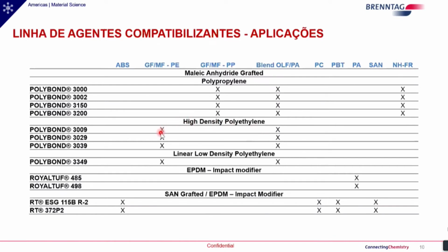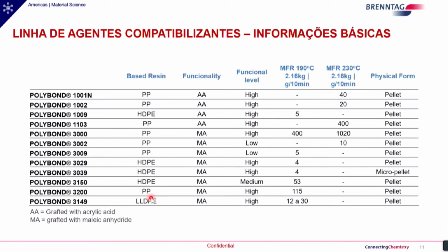In our line of products, we also have agents for high-density polyethylene, linear polyethylene, impact modifiers, and impact modifiers for styrene materials, polycarbonate, PBT, ABS, and others as well. Now focusing on the compatibilizing agents themselves and the sheet for the materials, we have different functionalities focused on two different principles. So we have acrylic acid based and also maleic anhydride in different functional levels or dosing levels, and also with different rheologies.